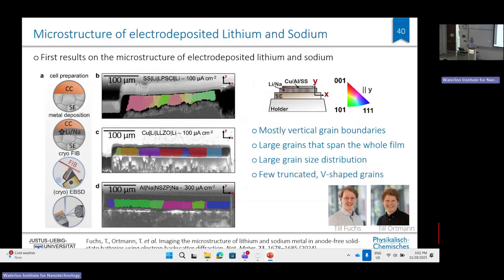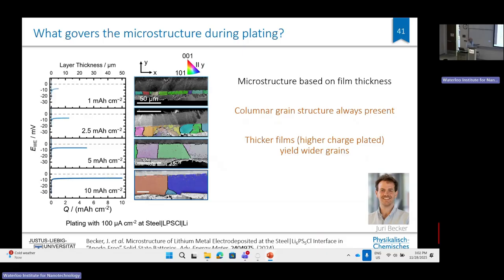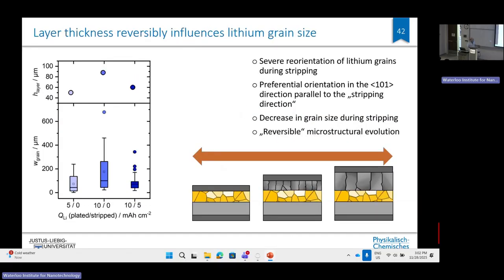In fact, we never got small-grained lithium. This lithium that is being electroplated is so pure that nothing stops it from growing and growing to large grains. So you see, with making it thicker and thicker, the grains grow and grow. We are still on the way to better understand what is going on, together with colleagues in metallurgy. But meanwhile, we know that it seems to be even reversible. So grains grow with thickness, and if you then strip, the grains shrink again. It's really interesting from a crystallographic and metallurgical point of view.